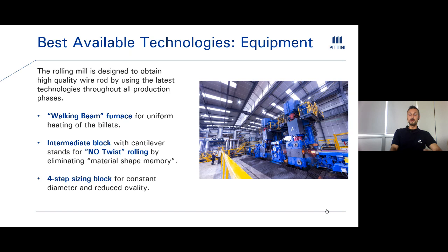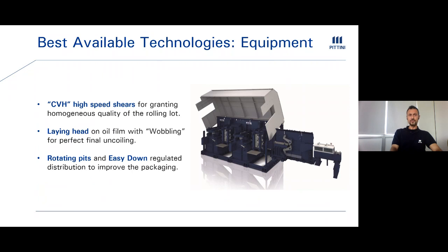And these are mainly related with, for example, superficial defects on the wire rod. And then the final step, the sizing block, that is the final step of the rolling. That guarantees a best sizing process. Concerning other examples about the equipment on the line, we have two other things. The first is connected with a high-speed shear that is able to crop the head and the tail of the product. So with this equipment, we are able to guarantee best homogeneity along the coil and defect-free tips of the coil.